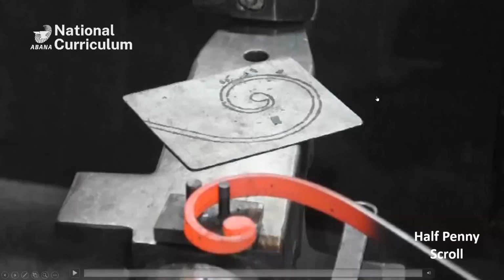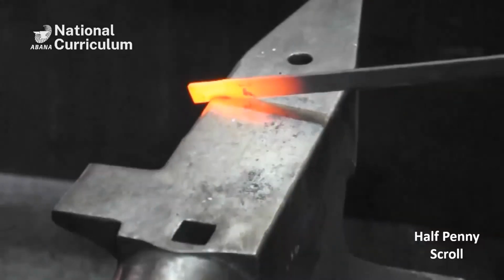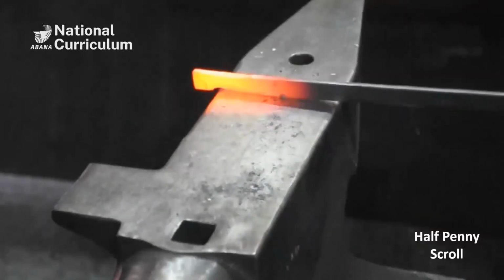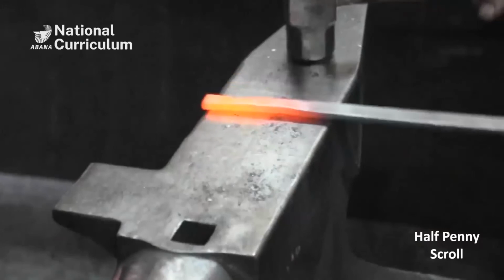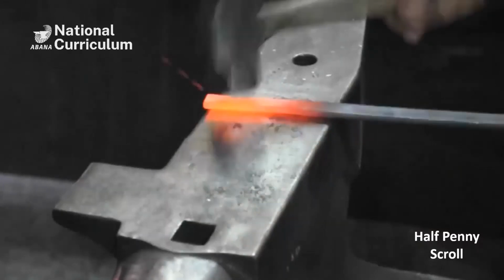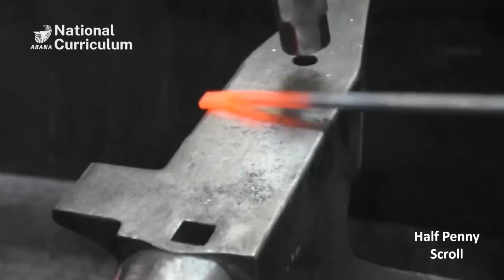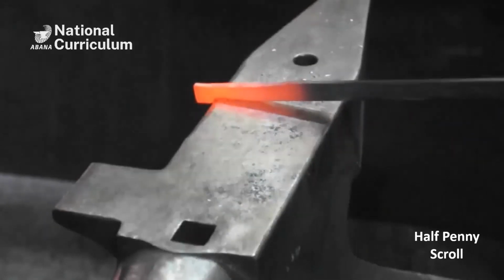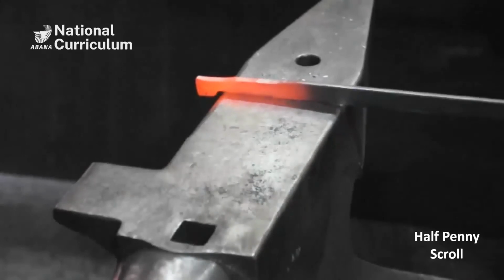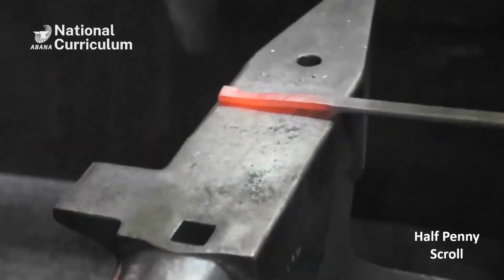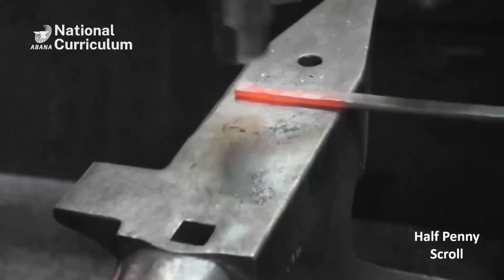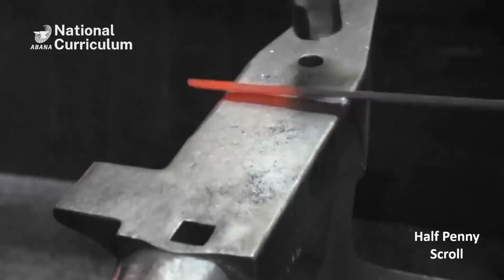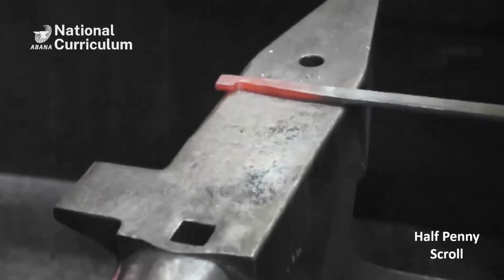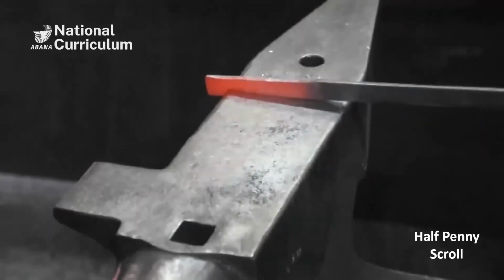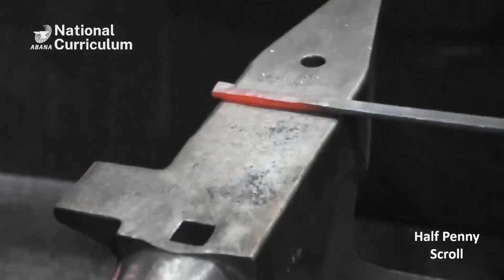How does this work? Again, a little video. Okay, I go to the far end of the anvil. I make my indentation, and as we've seen before, you don't start laying the piece flat on the anvil, hold it up a little bit to have that corner bite in there. And of course, it's a very rounded corner so that it doesn't bite too much, so that you don't get a cold shut there. Because when you curl in your end, that cold shut can't be corrected anymore. You just have to start over again.